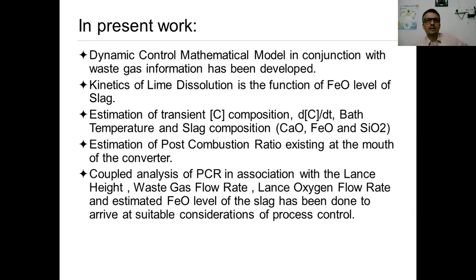In the present work, I developed a dynamic control mathematical model in conjunction with the waste gas information. The kinetics of lime dissolution is assumed to be a function of the FeO level of the slag. Then we have estimated the transient carbon composition, decarburization rate, bath temperature, and slag composition like CaO, FeO, SiO2. Only three components I have considered because they are the vital components. Then the post-combustion ratio existing at the mouth of the converter has been estimated. Then a coupled analysis of the post-combustion ratio with the lance height, waste gas flow rate, lance oxygen flow rate, and estimated FeO level of the slag has been done to arrive at suitable considerations for process control. That means with all this coupled control, we can predict the nature of the slag, whether the slag is dry, whether the slag is liquid, or whether slopping is likely to occur, and so forth.